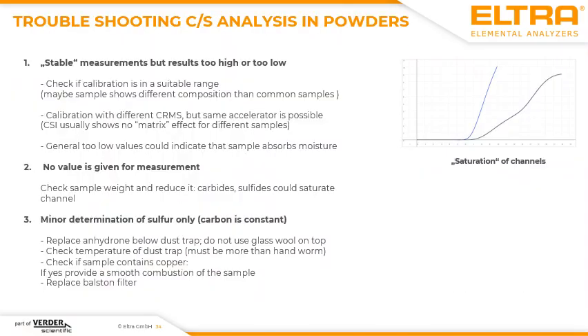At the end of the topic of carbon sulfur analysis, I would like to summarize it like this. For example, when you are observing trouble in analyzing your sample, you usually have different use cases. For example, on the one hand, you could have stable measurements, but the result is too high or too low. In such cases, I would recommend checking if the calibration is in a suitable range.